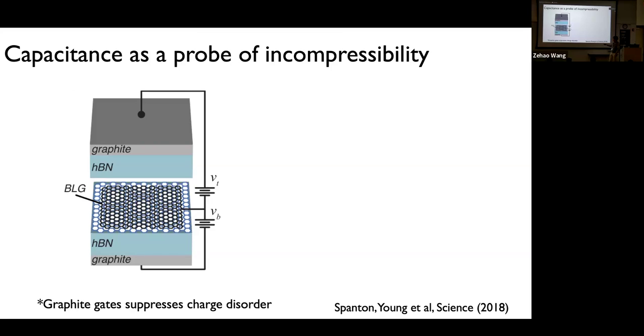The device geometry that they fabricated looks like this. You have a top gate, and then you have your sample of interest, bilayer graphene aligned with HBN, bilayer because it's more tunable. And then on the bottom side, you have another graphite. The quantity that they measure is capacitance, more precisely the penetration capacitance. You can think of it as applying a small AC voltage and trying to sense the electric field that the top gate can feel.